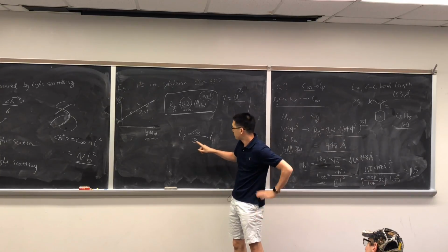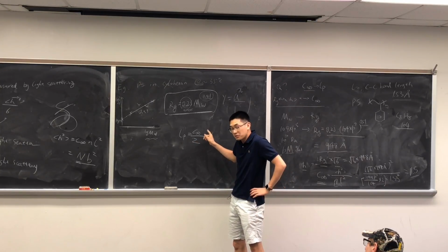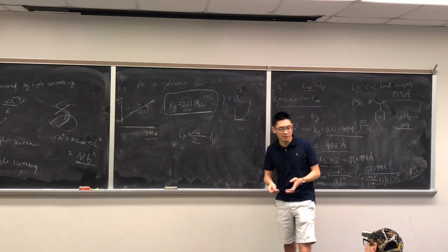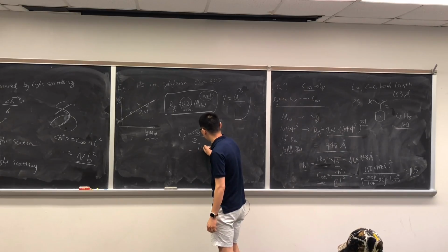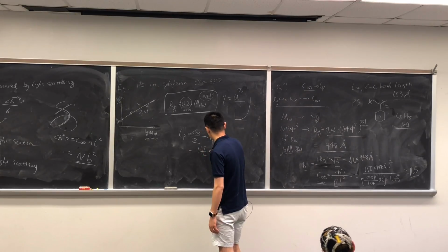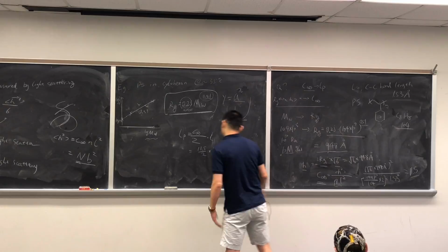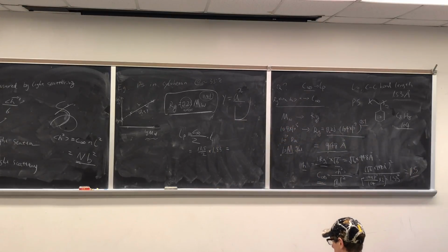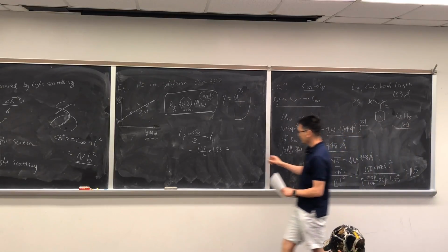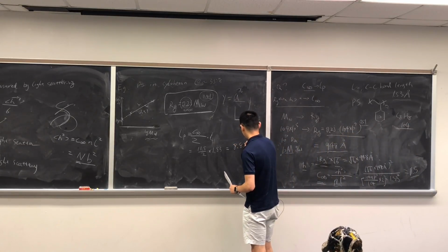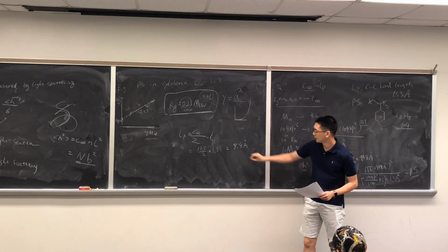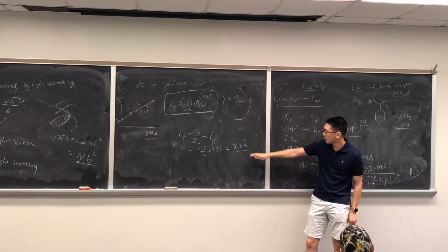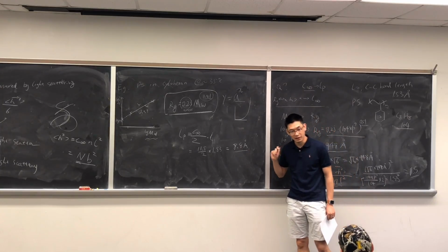LP is proportional to the characteristic ratio divided by 2 multiplied by the monomer bond length. If we do this, it is 11.5 divided by 2 multiplied by 1.53, and you can get the persistence length. So this is about 8.8 angstrom.